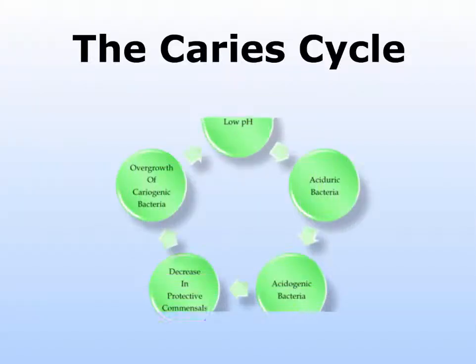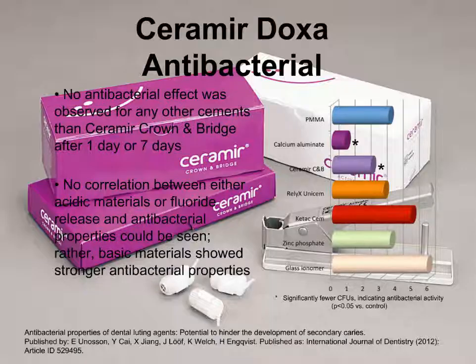antibacterial. Cariogenic bacteria are both acidogenic, producing acid, and aciduric, growing well in an acid medium. If we take away that acidic environment in which they proliferate by providing an alkaline pH, we can interrupt the caries cycle. In this study published in the International Journal of Dentistry, Ceramir was the only cement that provided an antibacterial effect after 1 to 7 days. In our fluoride-releasing materials, the fluoride released is bound up after only a short period of time, thus its antibacterial effect is limited. Furthermore, there was no correlation evident between either acidic materials or fluoride release and antibacterial properties. Rather, basic materials showed stronger antibacterial properties.